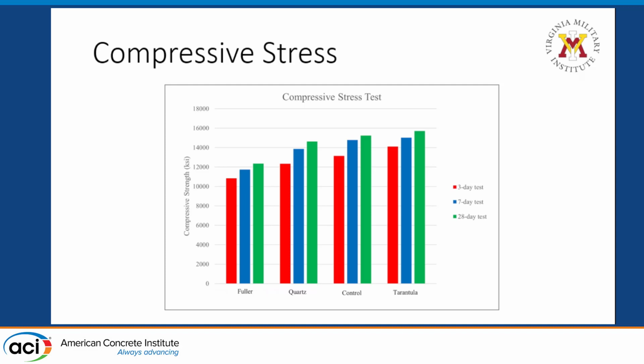This is the results from the compressive stress test. So each bar signifies an average of 6 trials, and the order of strength that we were able to reach from strongest to weakest was tarantula, control, quartz, and then Fuller.